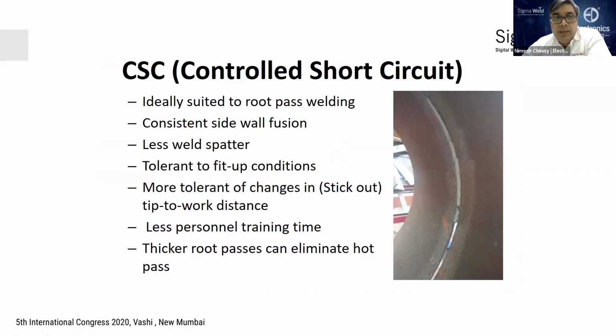So it's ideally suited for root welding, consistent sidewall fusion, lesser weld spatters, tolerance to fit up conditions, also more tolerant to changes in stick out, tip to work distance, and the machine automatically accommodates for it. Lesser time to train the personnel and thicker root passes to eliminate hot pass.